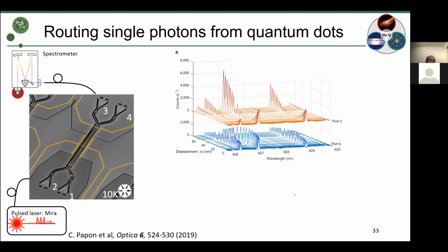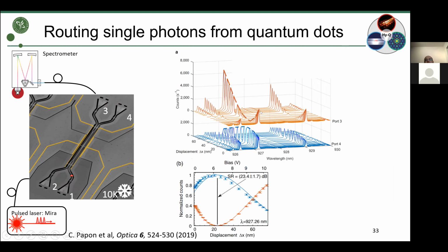And we can do that with quantum dots as well. So we can identify a single dot, excite the dot, and then look at the output again and see what comes out. And actually what you see now are the sharp spectral lines that are single quantum dot transitions that we're looking at. We can just look at one of these and trace the behavior, and we can find similar splitting ratios, similar extinction. And it operates very well, and it's compatible with the quantum dot.